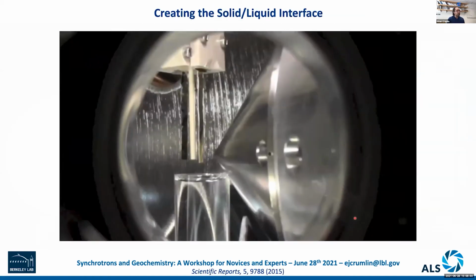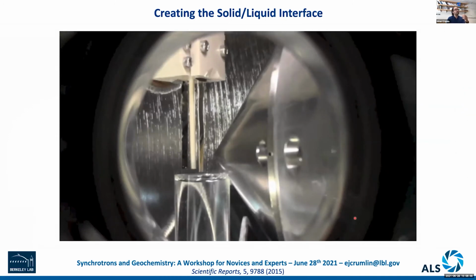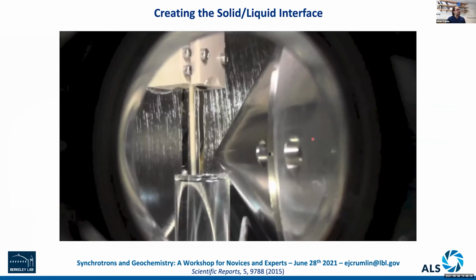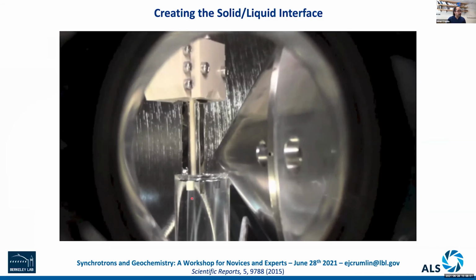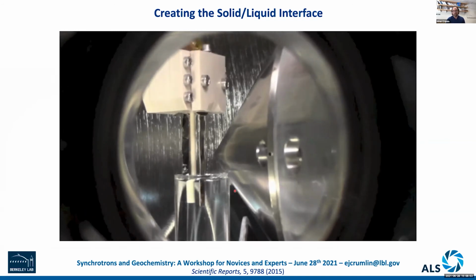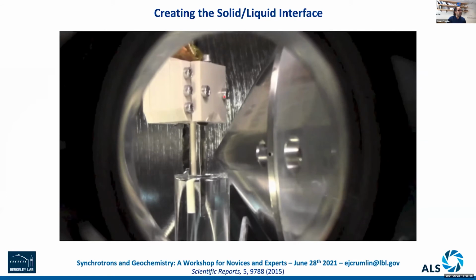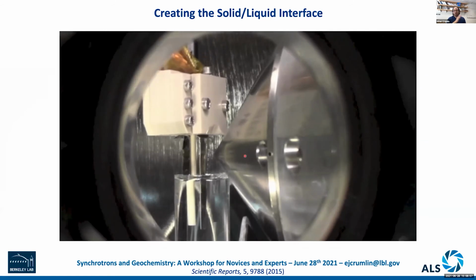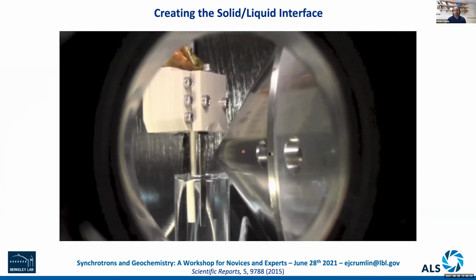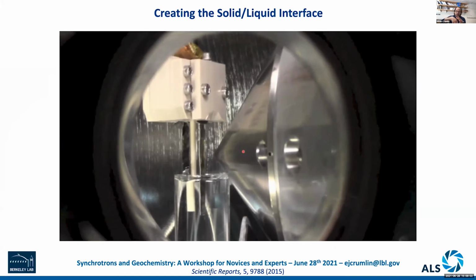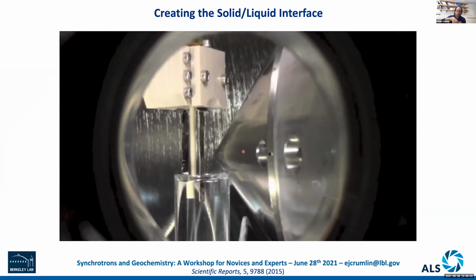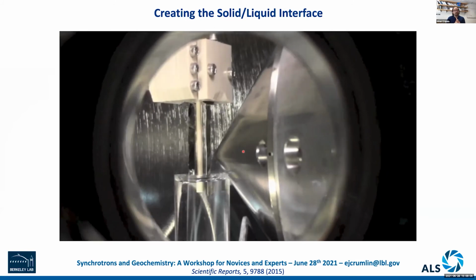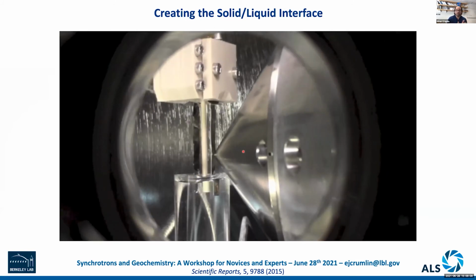And so now we can apply this to looking at interfaces more explicitly. This is what it looks like and how we set up some of these types of interfaces. This is what we call a dip and pull technique. We literally will have a beaker of our liquid that we're interested in looking at. This whole chamber will be saturated with water vapor at this point. So it's 100% humidified. As long as we get a wetting interaction, we'll dip down, pull up. As long as it wets, we can form a very thin film that's around 10 to 30 nanometers in thickness of that condensed phase. And as long as it's continuous, we're able to do electrochemical reactions.